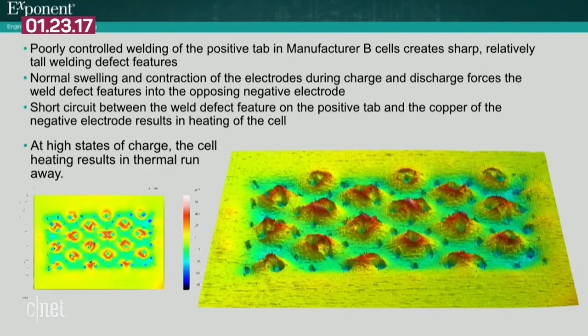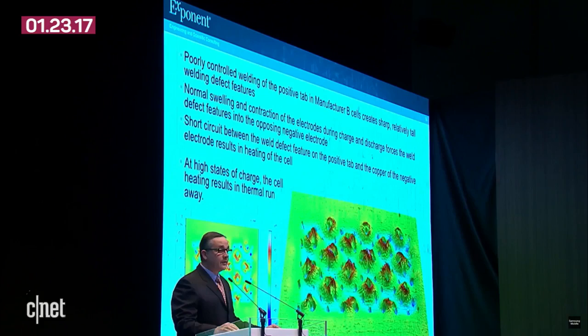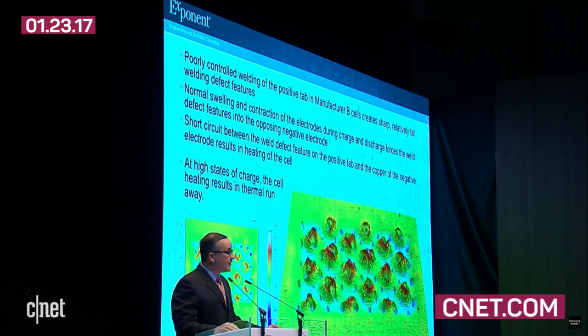Normal swelling and contraction of the electrodes during charge and discharge forces the weld defect features into the opposing negative electrode. Short circuit between the weld defect feature on the positive tab and the copper of the negative electrode results in heating of the cell. At high states of charge, the cell heating results in thermal runaway.